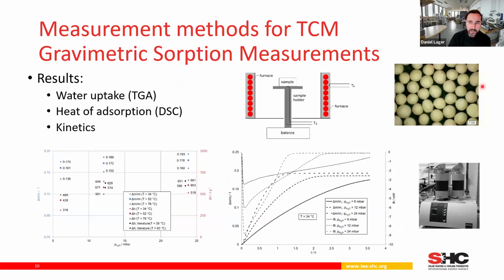Here you see an example for a zeolite. These are pellets of a zeolite 13X. And we measured with that, with a so-called thermobalance, the water vapor uptake at different pressures. And this is shown here in this graph. So here you have on the x-axis the pressure of the water vapor, and on the y-axis the water uptake. And you see the higher the pressure is, the more water uptake I get. And this is one result you can get out of this gravimetric sorption measurements. Additionally, you can also get the so-called kinetics. So how fast is the gas adsorbed or desorbed in this process.